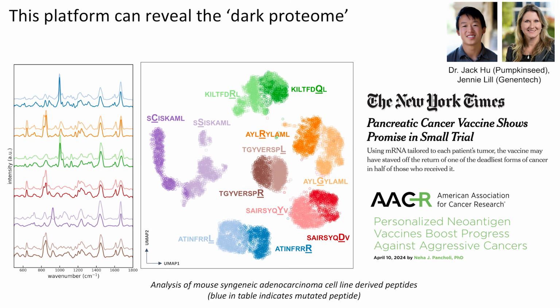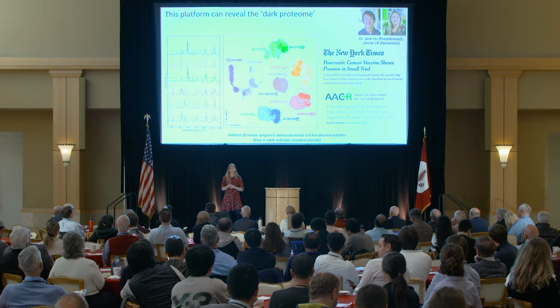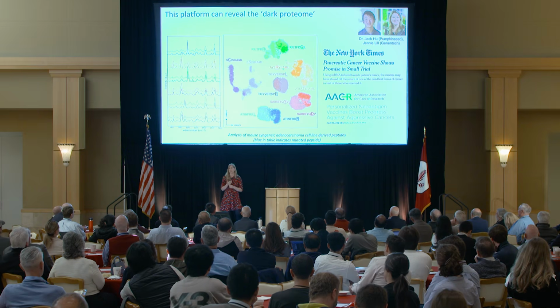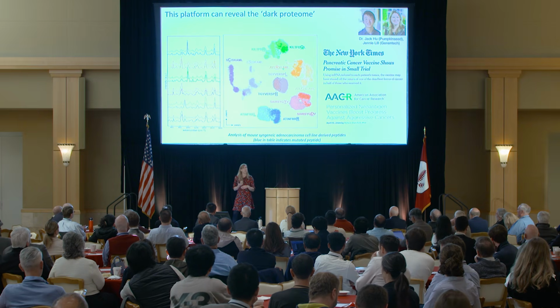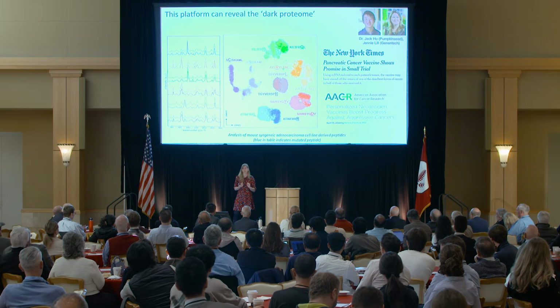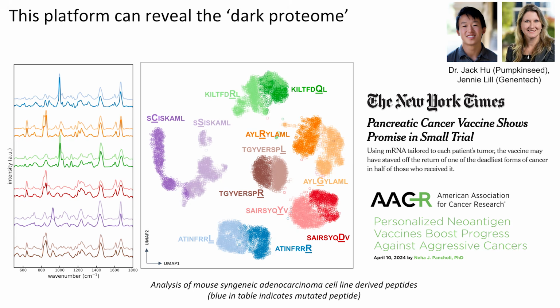But in particular, they're interested in understanding immunopeptides. These are short protein fragments that are expressed on every nucleated cell and serve as beacons to your immune system as to whether a cell is healthy or diseased. And it's very challenging to figure out those peptide sequences with state-of-the-art tools like mass spectrometry, especially when you're looking at an individual patient sample, because mass spec ionizes your sample and you lose over 99% of the information in there. And when it comes to looking at the differences between healthy peptides that all of our cells have versus mutated ones, like in cancer, there's only one amino acid or one letter that's different, so it's extremely challenging to get that information. But here you can see projections of some of the Raman spectra between healthy and mutated peptides.